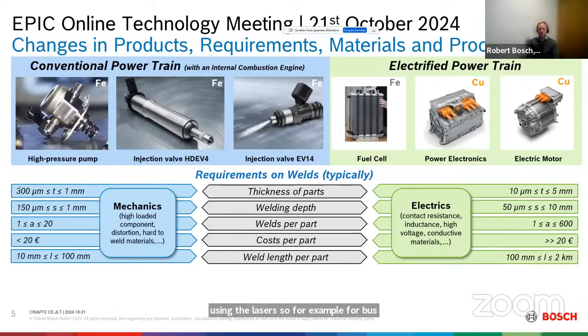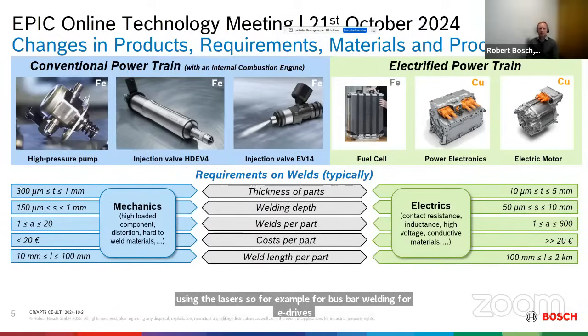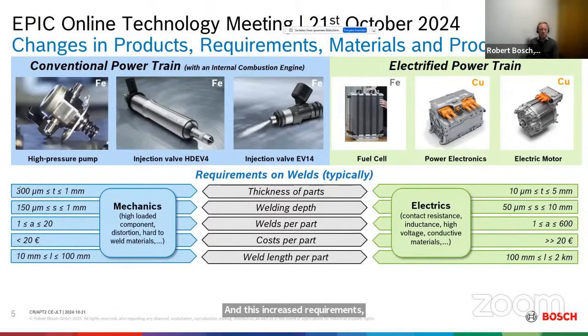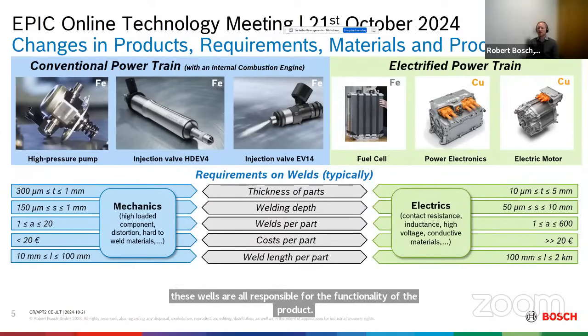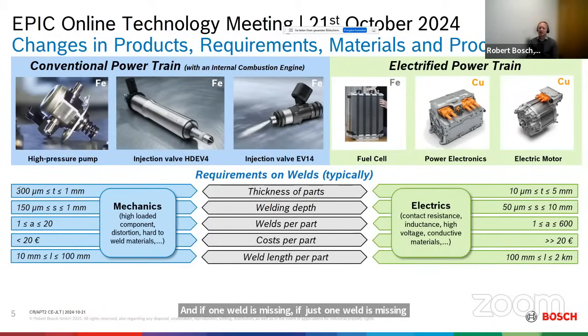And this increased complexity will be much more pronounced if we look at the welds per part. We came from 1 to 20 welds per part, for example, for the high pressure pumps, and now we end up with 1 to about 600 welds per part. And these welds are all responsible for the functionality of the product. If just one weld is missing or has a failure, the whole part can be destroyed.